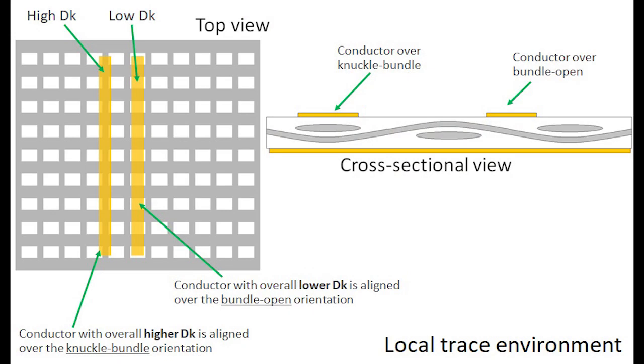Shown here on the left is a top view of a glass weave pattern, and laid over it are signal conductors, assuming a microstrip structure with the ground plane on the bottom, which is not shown in this picture. The glass weave is the gray grid pattern, and the conductors are the ghosted yellow pattern. One of these conductors is labeled as high Dk, and that's the conductor aligned to the glass weave in such a way that it's right over a run of bundles, knuckles, bundles, knuckles of the glass weave pattern.